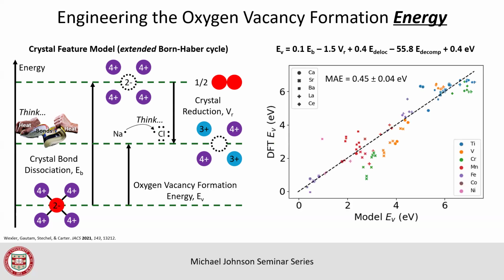So we basically build a model that encodes these pieces of information. We calculate that quantity. We actually do a bunch of brutal calculations of this energy required to knock the atom out using ab initio DFT. This is just one way of doing quantum mechanics on the system. And what we find is that, well, actually, we can write down a very simple linear equation. So it's just a bunch of slopes and intercepts. And we can write down some equation that can basically fit that. So this complex quantum mechanical problem, what it's saying is that you can boil it down to fitting a line in Excel. And that's what we did.